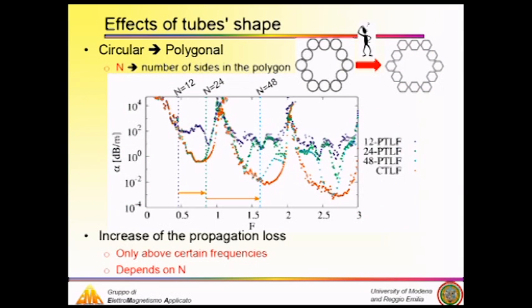Okay, now moving on, let's consider what happens when we change the shape of the cladding tubes. In particular, let's see what happens when we change this circular shape to, in general, a polygonal shape with n sides. Here you can see a comparison. The red dots represent the circular case, and as you can see, it gives the best performance over the entire spectrum. Whereas the polygonal ones have some additional resonances, additional increased losses at the center of the transmission window. In particular, these vertical lines highlight the fact that the higher the number of sides, the higher the frequency at which these extra losses appear.